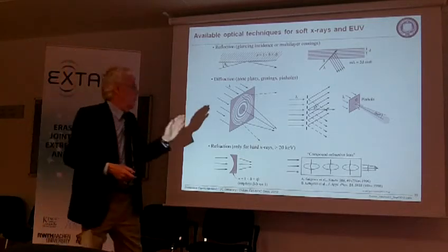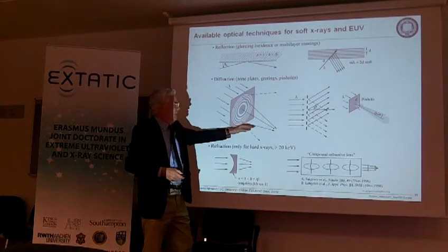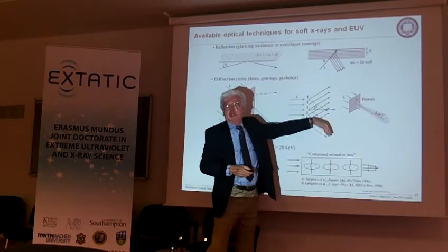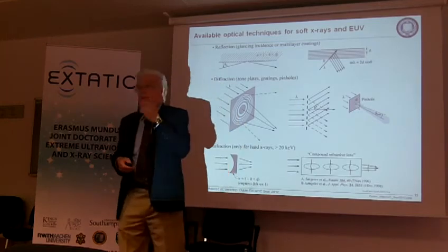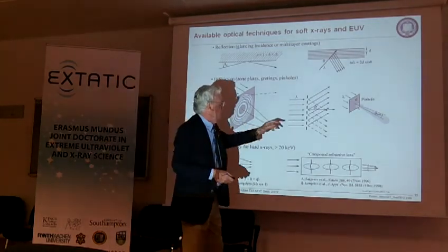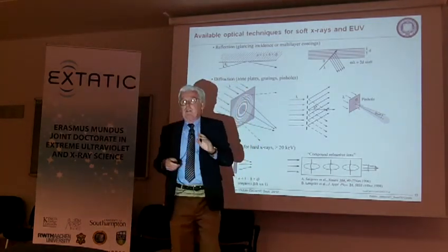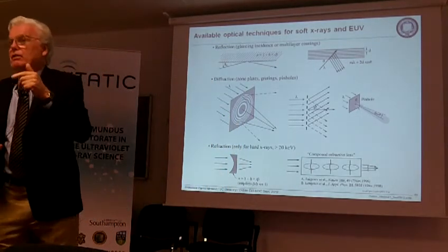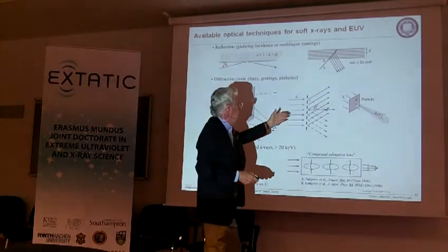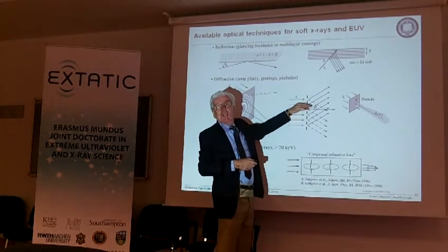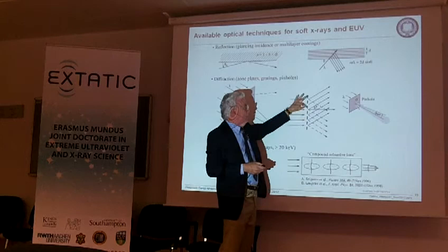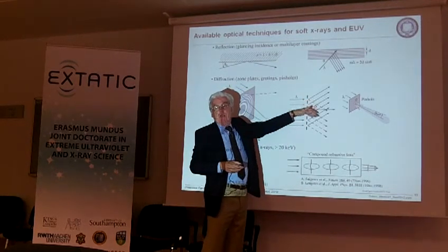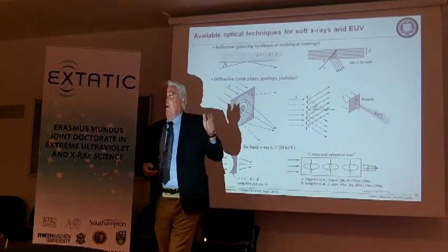If you use gold at the soft X-ray wavelengths, then this will be totally opaque, and that's where you get the 10% efficiency into either order. But depending on the photon energy and the material, if you use nickel and work just below the nickel edge so it's not quite so absorbing, you can get a phase effect. You'll get not 100% absorption, but a little bit of a phase reversal as it goes through. So you have to make the thickness right, and you can increase the diffraction efficiency above the 10%.